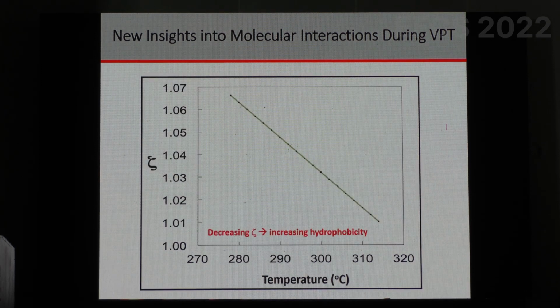The second interesting thing that the theory told us is that this parameter that captures the hydrophobic interactions has to have a temperature dependence, a very minute temperature dependence. If you look at the y-axis, it's a very small difference. So this is how subtle it is.